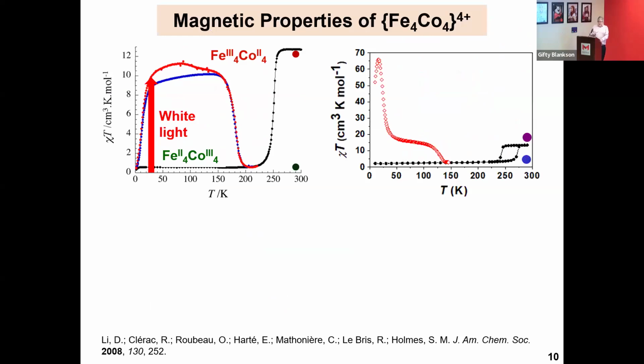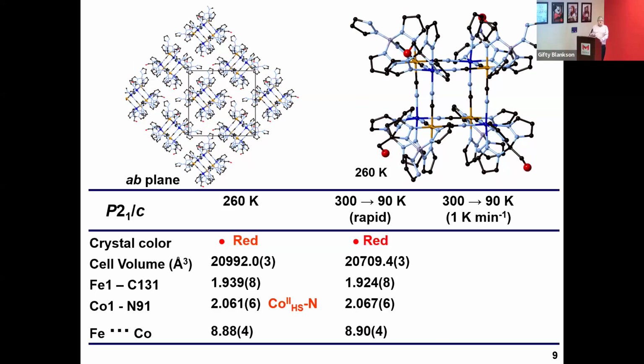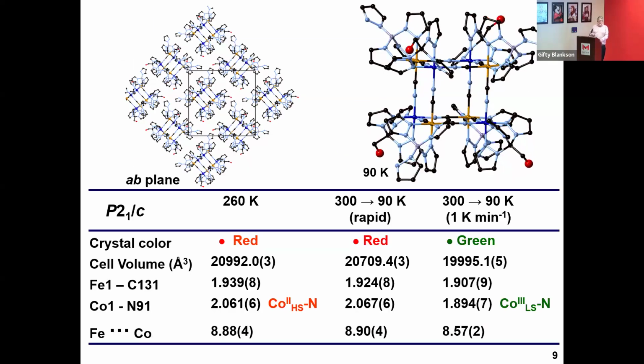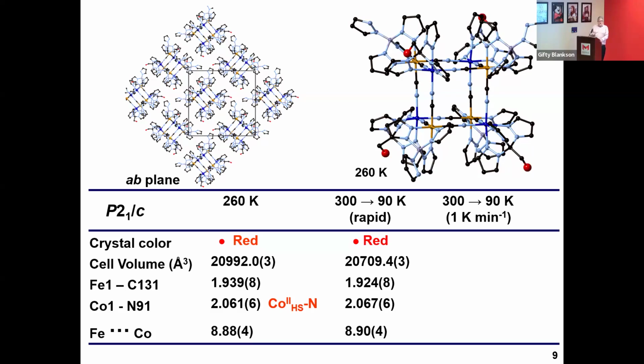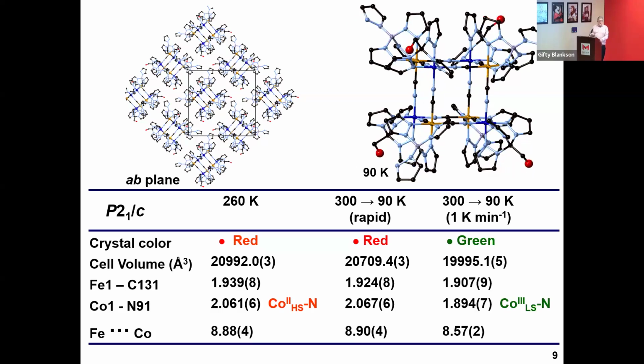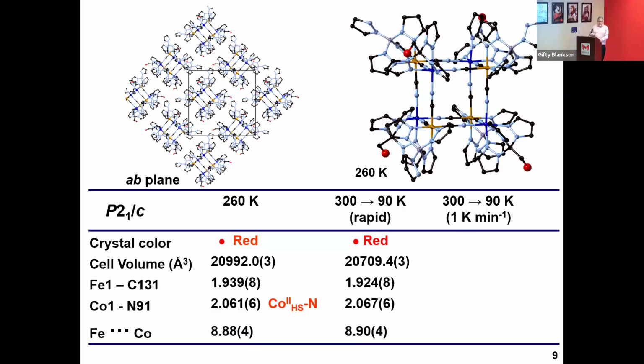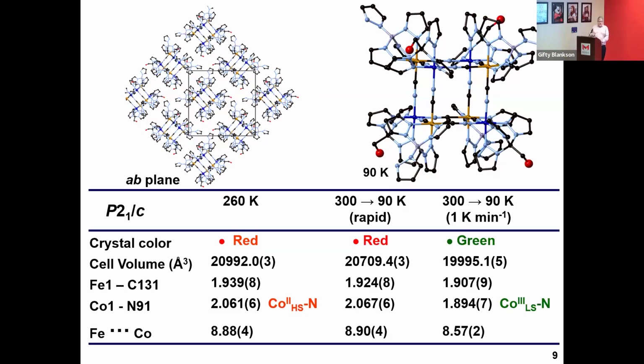But notice, lots of things are happening. It's that single electron transfer between the cobalt and the iron centers that is changing bond distances and angles a lot. And you're also collapsing the unit cell volume by quite a considerable margin. That's because of removing antibonding electrons at the cobalt site. When you oxidize it, it goes low spin.